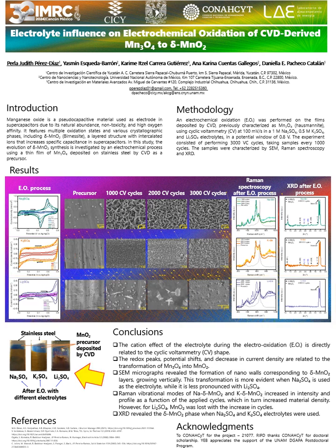Lastly, in this image, I present the physical changes the film undergoes during electrochemical oxidation. The Hausmannite films start with a blue color, which changes to gold when sodium and potassium sulfates are used as electrolytes. With lithium sulfate, the final coloration is more purple.